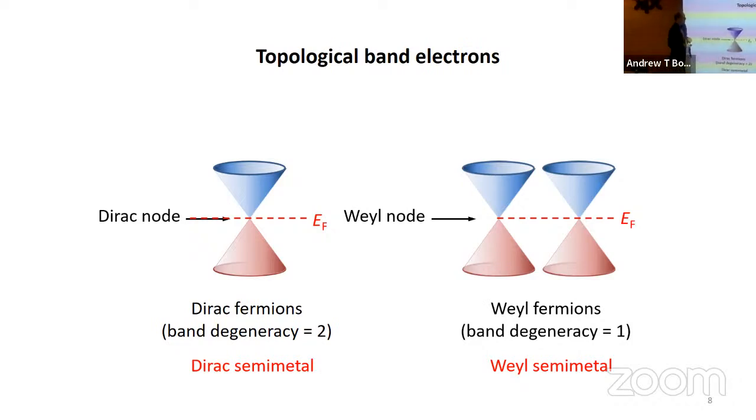The Weyl equation is interesting because the electronic excitations have a coupling between the spin of the electron and the momentum of the electron. That's why, in that previous picture of the topological insulator, the surface conduction states have well-defined spin direction. Again, if the chemical potential lies exactly at this point here, we have what's known as a Weyl semimetal.